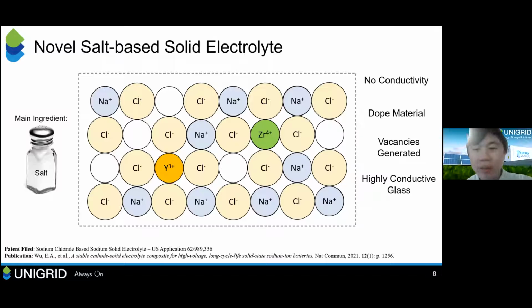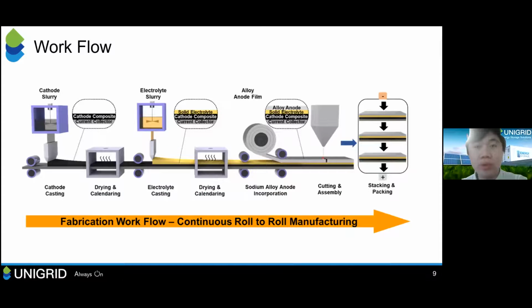So the entire material now becomes highly conductive, and because it is very disordered, it's quite glassy in nature. That means the whole material becomes an amorphous glass. Now we've optimized this process over many iterations, and we can now fabricate it in a quite simple single step using room temperature processes. So we don't have to anneal anything, we don't have to heat anything to very high temperature, and we can use low-cost materials starting with table salt to produce this. So this invention has been patented, and we obtained a license from our home institution in California. And we'll also publish this in some reputable journals in order to be as transparent as possible to demonstrate this proof of concept.